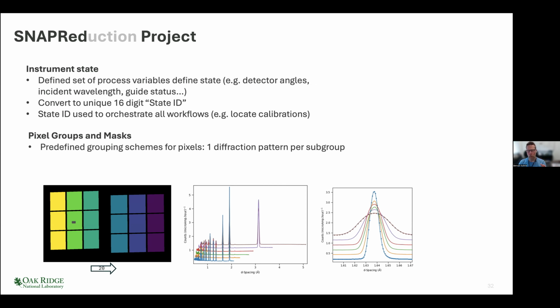We also support ways to combine these pixels. So generically, that is via pixel groups or pixel masks. And just to make concrete how this allows us to take this multi-dimensional data and make it easy to analyze and process, I've again got my little 2-square representation of the instrument here, each larger square representing a detector. And then within that, the 9 smaller squares, 3 by 3, are individual modules within a detector. And the color coding is encoding pixels that have been told you're in the same group. So all the pixels colored in yellow here are all being added together into the same diffraction pattern. So if I group them in this way, and you can see I have 6 different colors, that gives me 6 different spectra, which I'm showing here as a function of d.